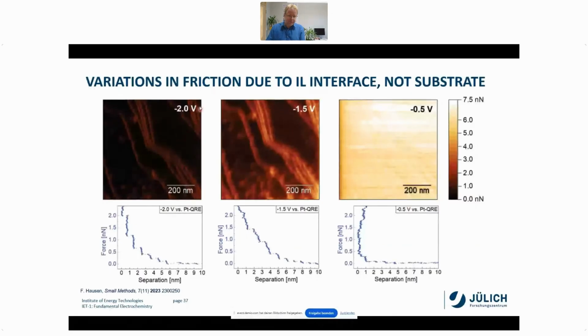So if you look at this interface again on the gold surface, minus 2 volt, minus 1.5, and minus 0.5, then we see that indeed the substrate, in this case the gold, you see here the steps, is not changed. You can see the step structure in all of these images. The color is again representing the friction.